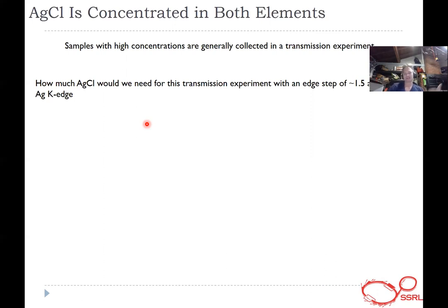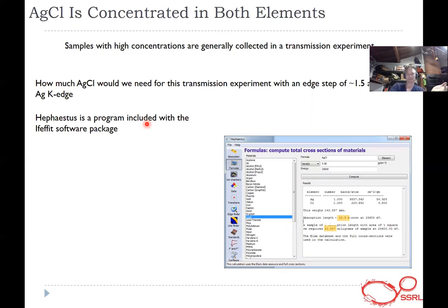An edge step, you'll learn about later, is how big the jump is from pre-edge to post-edge. You can be too low or too high, and the acceptable range is 0.1 to 2, depending on your situation. Hephaestus, which we talked about earlier, is included with the IFEFFIT software package and has a nice little formula, so you can compute the total cross-section of the material. You can put in your silver chloride here, look up your density for your material, or ballpark it as best as you can, and it'll spit out a couple of numbers.